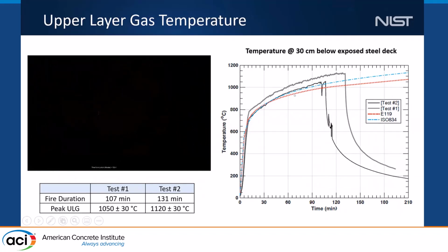And this plot basically shows the comparison between the average upper layer gas temperatures measured from test number 1 and 2 in comparison with the standard furnace temperature. As you can see, the test number 1 temperature was very closely related to the standard furnace temperature. Test number 2 also increased in a similar fashion, but was about 100 to 200 degrees Celsius higher than test number 1.